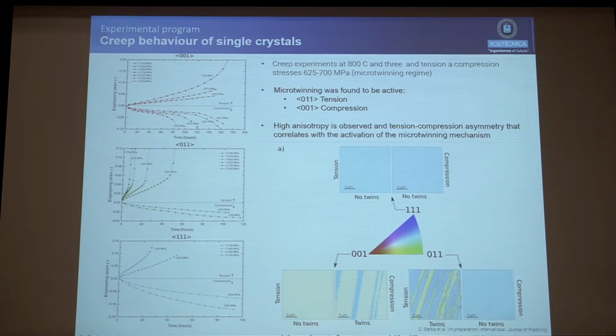In tension and compression, to see which mechanism was activated in each of the conditions. And we found that actually the material that is creeping at higher creep rates is the material that is twinning. So we can see the activation of microtwins at 001 orientation in compression and 011 orientation in tension. And the microtwin mechanism, as you can see here, is not symmetrical as it happened with mechanical twinning, because we did the opposite and we couldn't see it in tension or in compression in the same orientations.